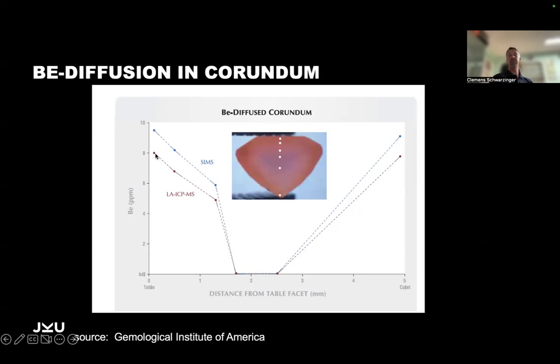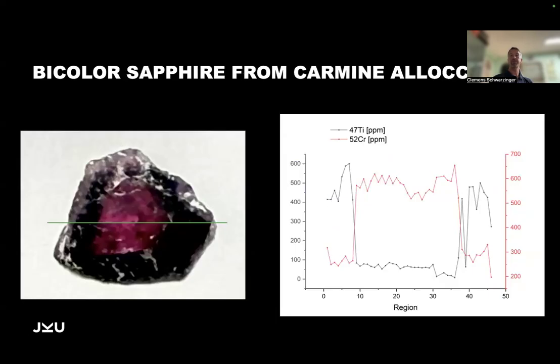And with laser ablation ICP-MS, you can see that you have a concentration at the rim of 8 ppm, going down to 5 ppm, in the core you have nothing, and back here at the tip, we get up to 8 ppm. I can tell you this is a rather high concentration of beryllium. Even just 1 or 2 ppm of beryllium would be enough to give the gem a nice orange color. This is one of the cases where laser ablation ICP-MS has become famous, being able to detect this beryllium treatment in corundum.